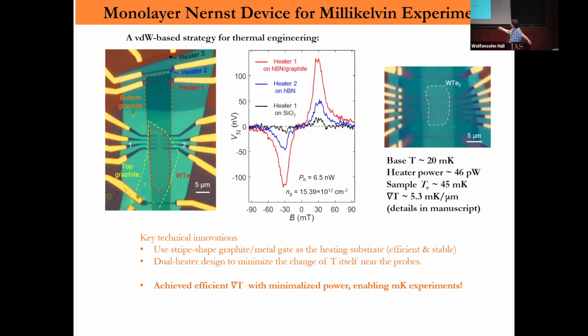So at the end, with this geometry, you can also bring the heater closer to the flake like this. Then we are able to generate a temperature gradient of 5 millikelvin per micrometer with only a power of 50 picowatts. It's very small, so we still keep temperature very low. The electron temperature of the sample is still on the order of 50 millikelvin. So what I'm saying is that we achieved to apply a tiny power while generating a good amount of temperature gradient, allowing us to measure the Nernst effect at millikelvin.